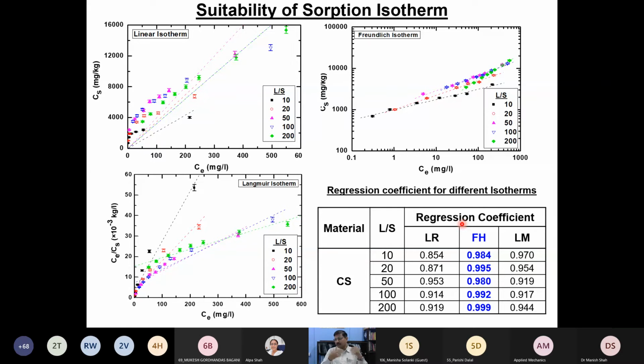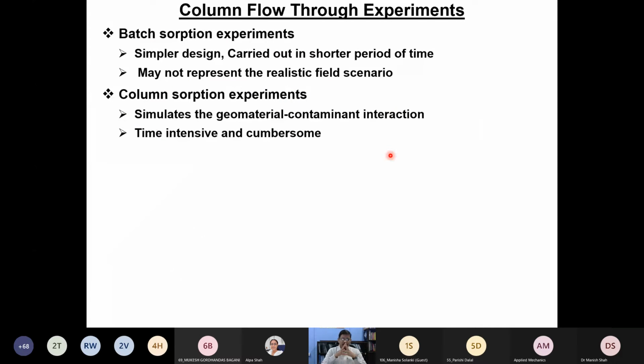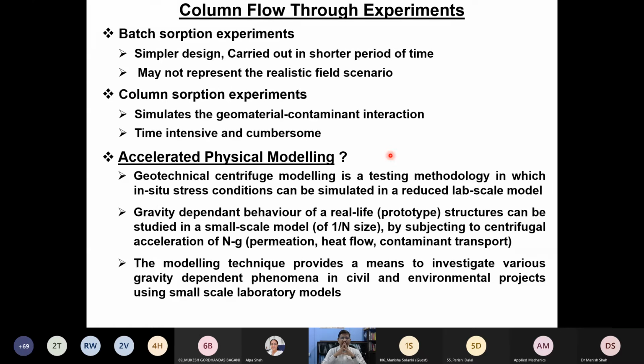But in case of a geomembrane and an organic contaminant, most of the time we may be very happy with the linear isotherm, or very seldom we may go to the Langmuir, but otherwise it is one simple way. But the drawback with these batch sorption experiments is that they are very simple and very easy to conduct, so they may not represent the realistic contaminant and sorbent interaction very precisely. The contaminant migration in real life is as if it is something like water flowing through a column of soil or a column of a liner. So in order to do that, column sorption experiments or column flow-through experiments are commonly conducted.